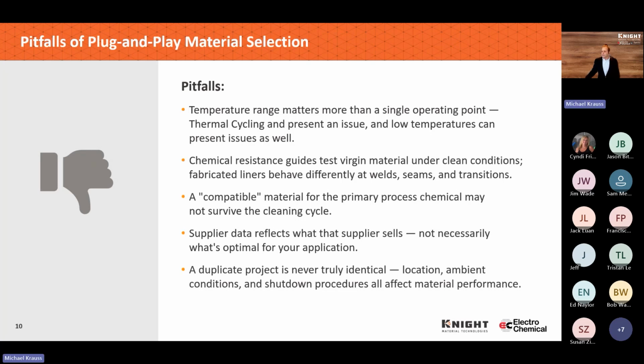The other thing is that the devil is in the details. You might say that we've got a 35% HCl line and think that that's the driving factor, and neglect that there's a bunch of organic chlorides in the ppm level that are floating through the system. Well, those small amounts of organic chlorides or other materials might be the difference between success and failure. So again, sharing information, helping understand what the entire chemical stream is, how everything operates, is really critical for success.